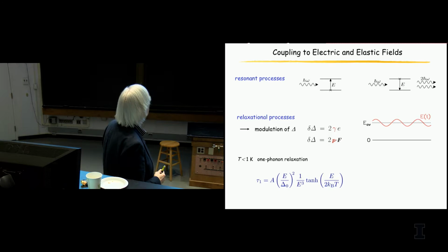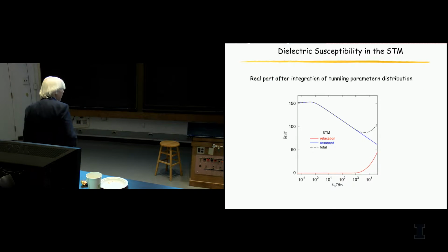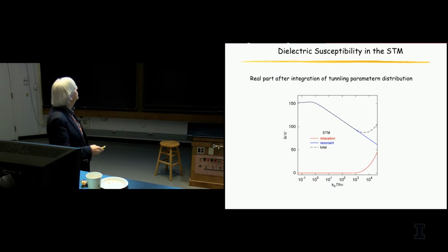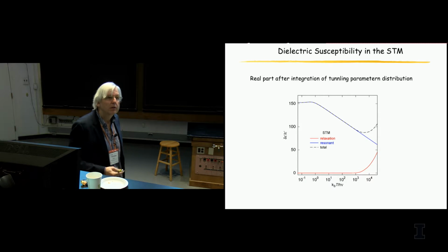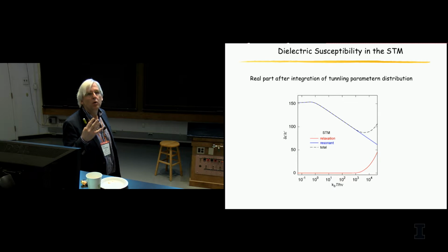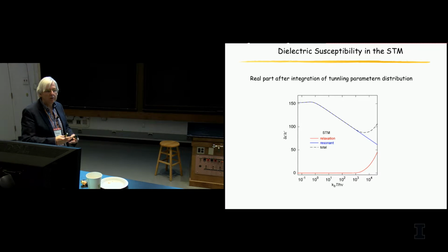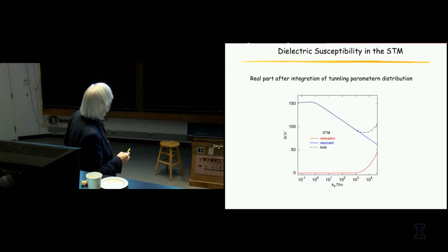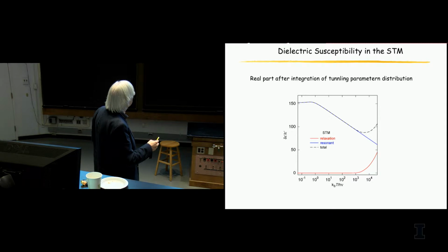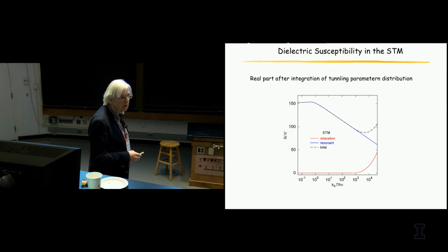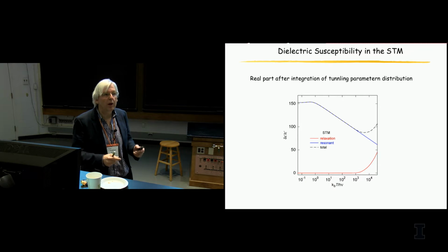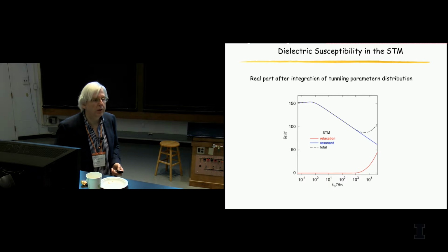That's all known. Now, if you integrate over all the parameters over this wide distribution, the tunneling model says we get a resonant contribution, which is logarithmic. This is a characteristic of glasses. This is in some ways identical to the linear dependence in the specific heat. It's just reflecting that you have a broad distribution. And then at some point, the system is fast enough at a finite frequency to contribute to the relaxational channel, and this is the red one here. So if you add this up, you find this minimum. And this is the point I want to make: we have a minimum here, and this tells you when the onset of the relaxation is.